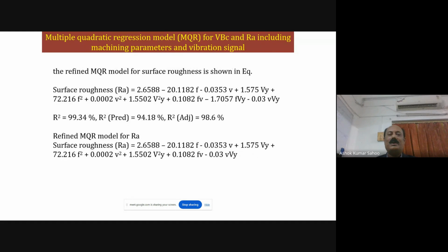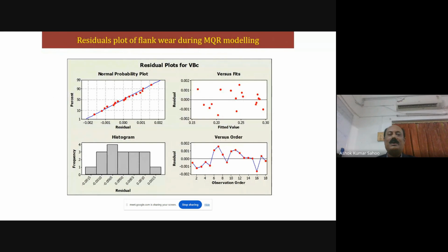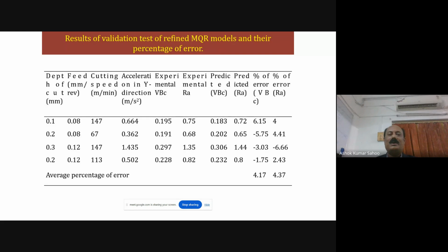R square is 98.6% for Ra, and these are the residual plots for flank wear and the roughness. Experimental value and predicted value are compared, and percentage of error for flank wear is calculated. It is less than 1%, and percentage error for surface quality is less than 1.2%, that is 1.22% only for the multiple quadratic regression model, MQR model, which is found to be very good.